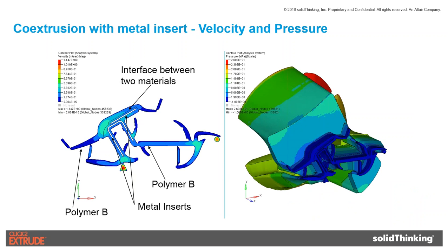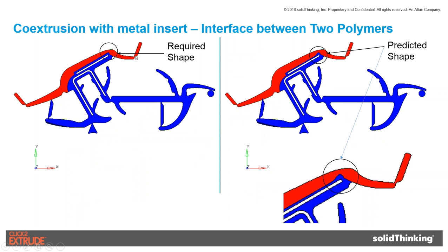So here I'm showing one test case where two metal inserts are coming into this profile and two polymers are extruded, and one is a U-shape and one is a flat metal insert. This was a real benchmark, and we compared with experimental data here. This was the desired shape of the die, but because of the differences in viscosity and the speed, the blue polymer was pushing in and taking the shape of the area of the red region, as you can see here.